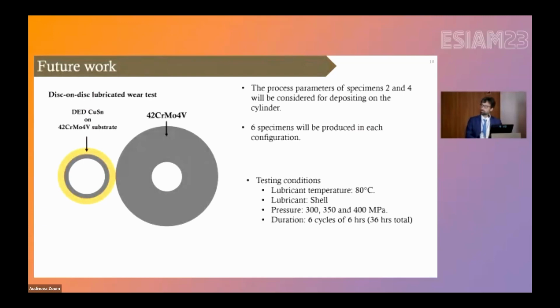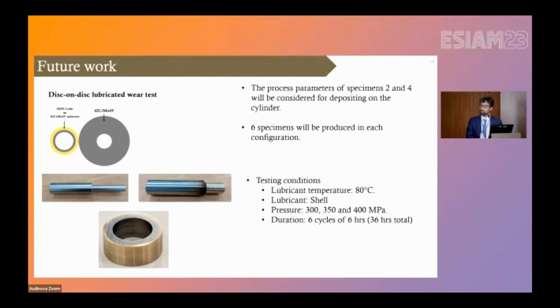Now we are in the process of carrying out disc-on-disc lubricated wear tests, in which we are able to apply much higher contact pressures representative of in-service conditions, with the aim of evaluating the capacity of the coating to sustain such high contact pressures. Okay, so here you see the first prototypes we have made. We turned a bar, and the bar was coated with the bronze layer, and then the bar was cut into discs for this kind of test.